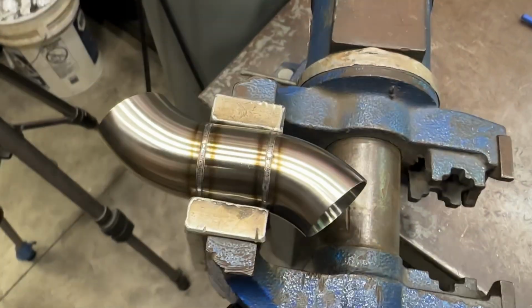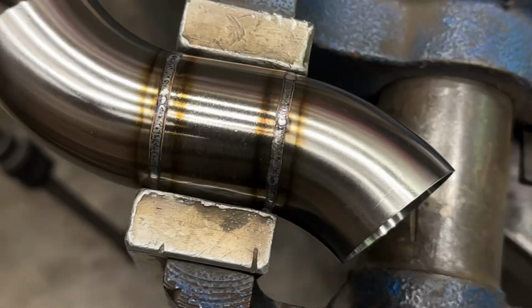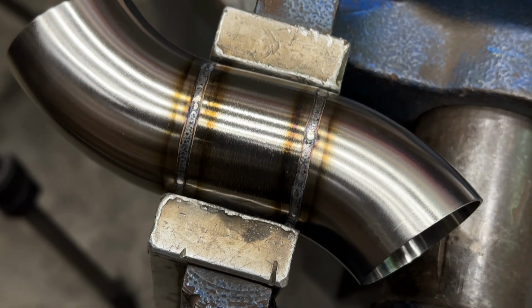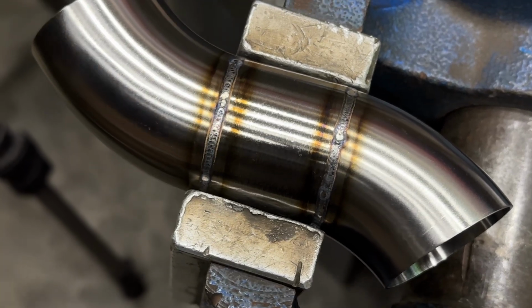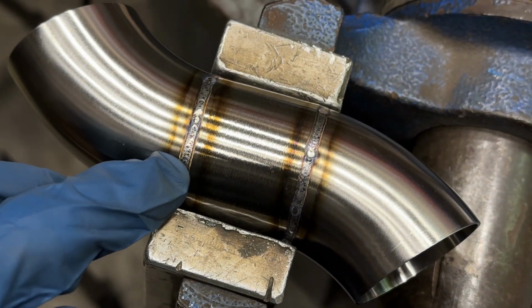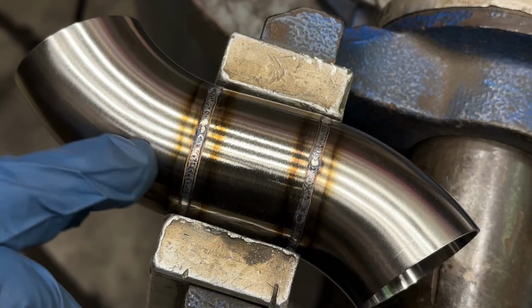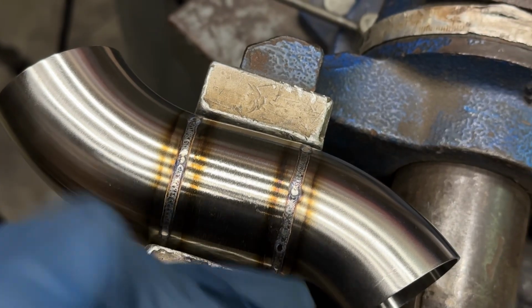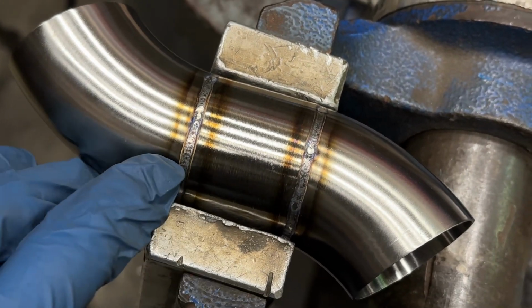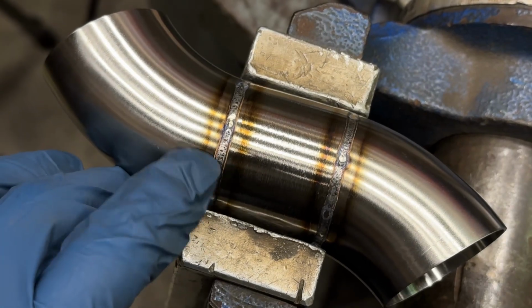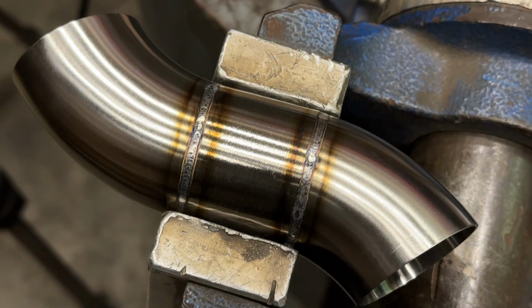And we can see already there's a bit of an aesthetic difference, at least just on the outside of the piece. This weld on the left that was purged, you can see through it, although the puddle, or the weld, is a little bit muddy, and that's just a function of this material. You can see less contamination and coloration on the outside, which says to me that the purge was preventing the weld from picking up a bunch of crap on the inside.